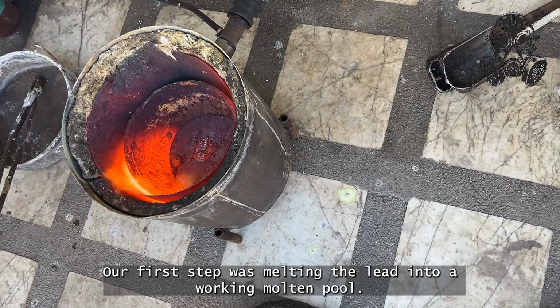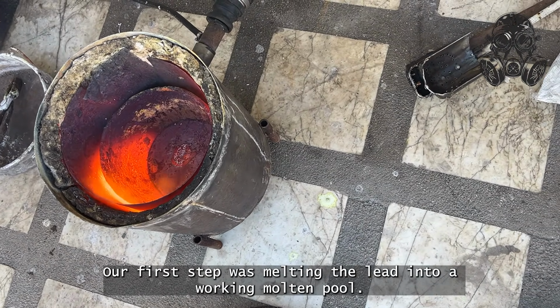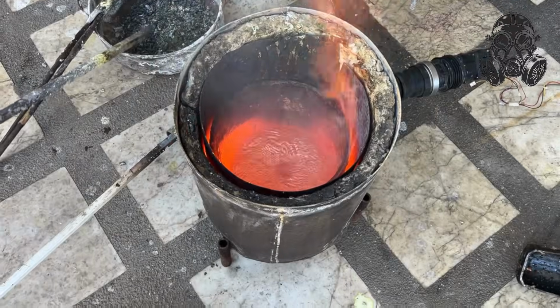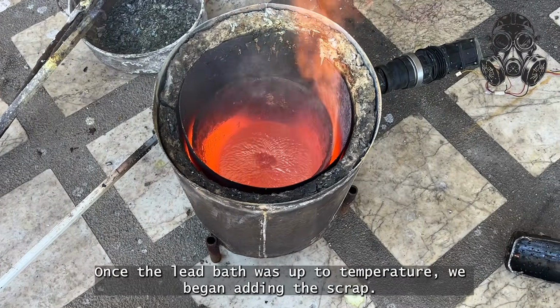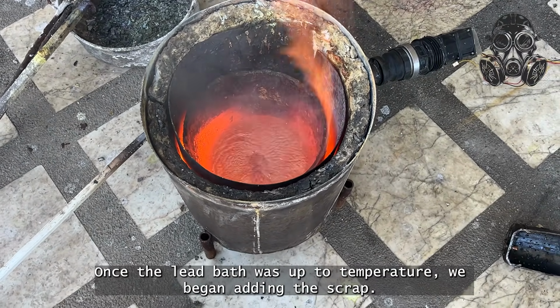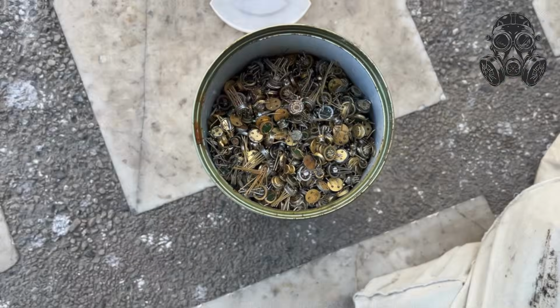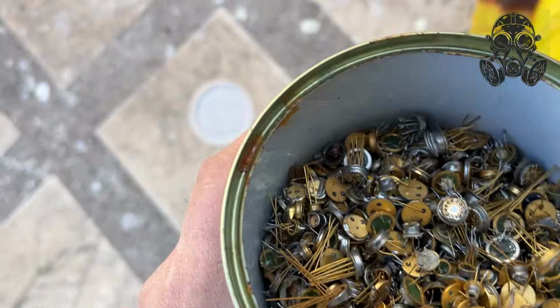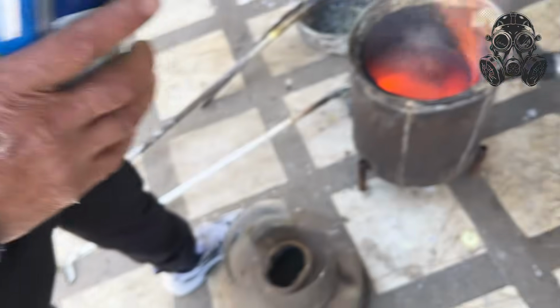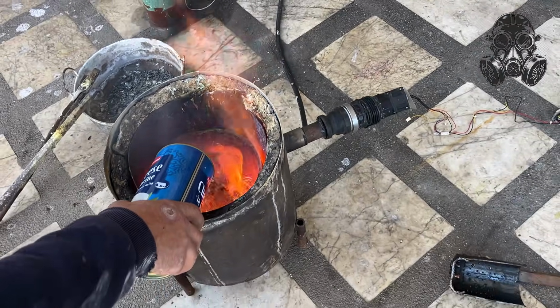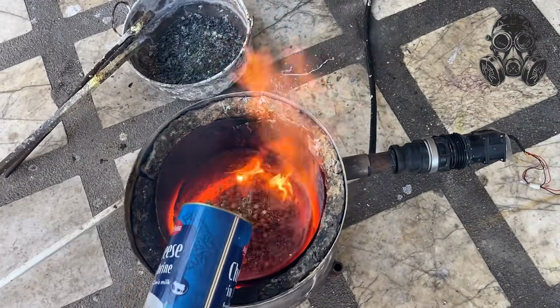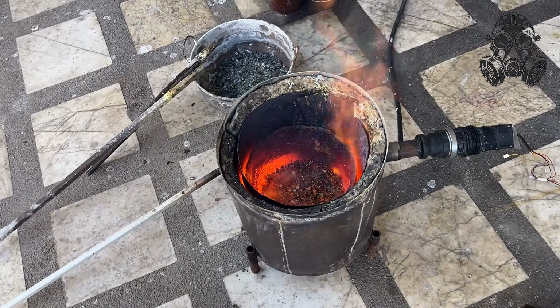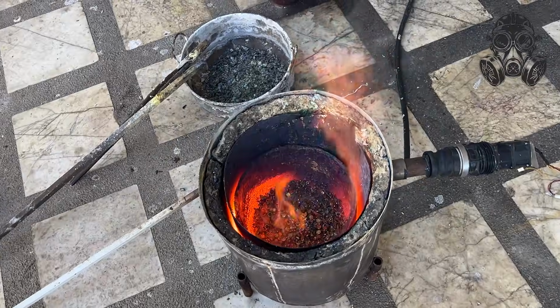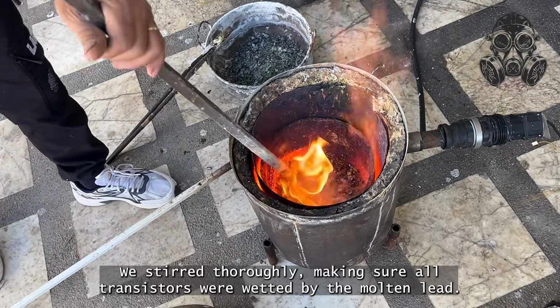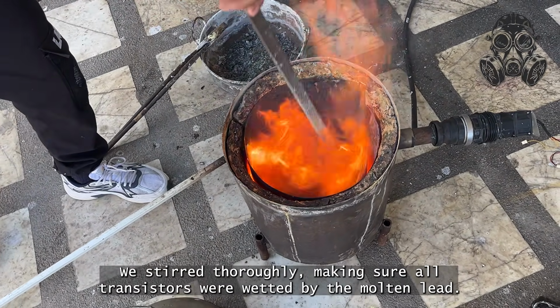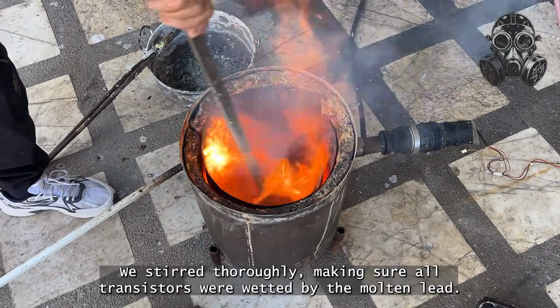Our first step was melting the lead into a working molten pool. Once the lead bath was up to temperature, we began adding the scrap. We stirred thoroughly, making sure all transistors were wetted by the molten lead.